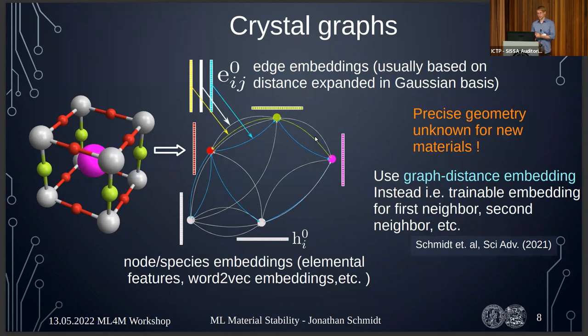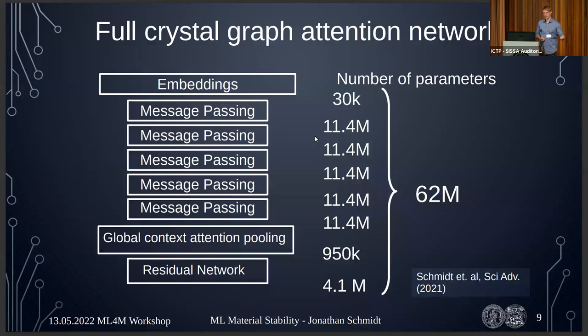Our idea was to take the physics out and just say: the atom is the first neighbor — we don't care if it's one angstrom or two — and use an embedding for the graph distance (first neighbor, second neighbor, and so on), then throw more parameters at it and let the model learn. Our models use attention mechanisms, somewhat similar to natural language processing, and end up as message-passing networks with around 60 million parameters.